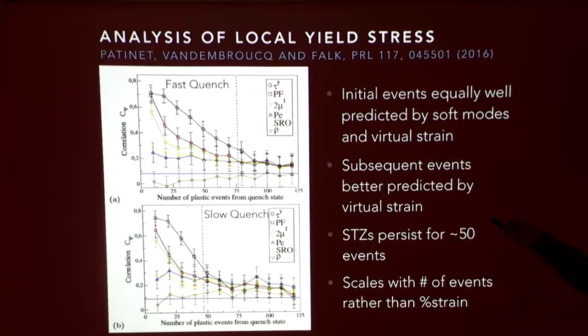PF is participation fraction, that's the soft modes, using the eigenvectors to pull out the soft modes as I was talking about earlier. 2 mu is the lowest local shear modulus. PE is the potential energy per atom. Yellow is the short range order topologically measured measure I talked about before. Rho is the local density. And the blue line here is what you would expect for just random white noise.